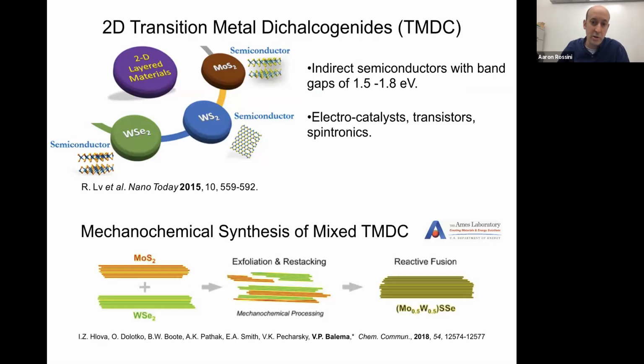What we got interested in looking at for these materials is we have a collaborator in the Ames lab, Viktor Balema. He's a mechanochemist, so his group has been developing methods to synthesize mixed transition metal dichalcogenides. So for example, they'll take molybdenum sulfide and tungsten selenide, ball mill them to mix them together, and then they can thermally anneal them to get mixed chalcogenides. And this is one way that you can tune the properties of these materials, by tuning the composition in this way.